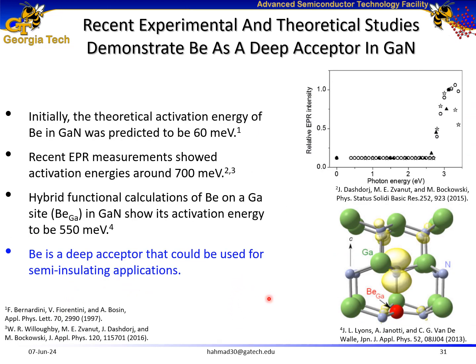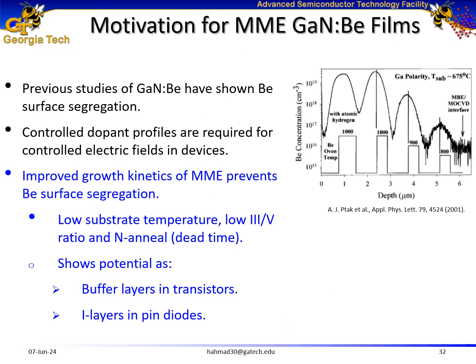Initially, the theoretical activation energy of beryllium in gallium nitride was thought to be 60 millielectron volts. However, later experimental studies showed its activation energy in the range of 500 to 700 millielectron volts. So beryllium is actually a deep acceptor in gallium nitride that could be used for semi-insulating applications.